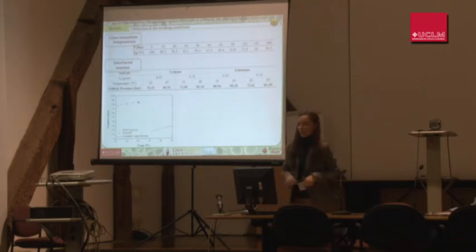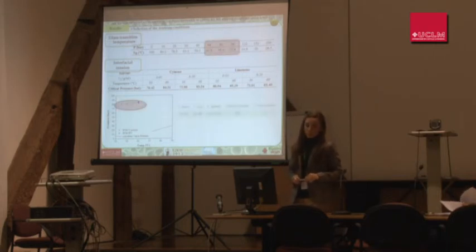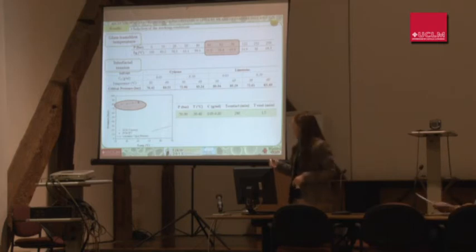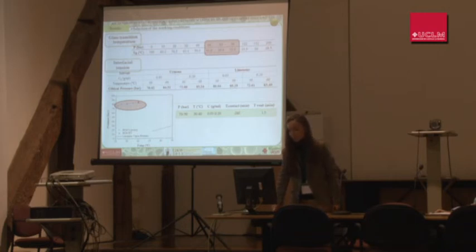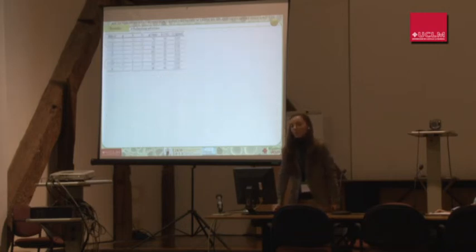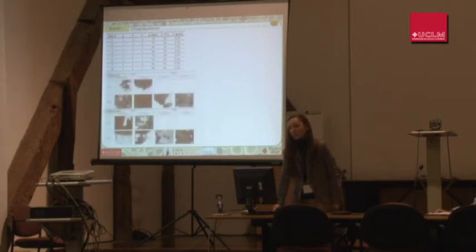So, as the foaming process should be carried out around the Tg zone and in a place where the interfacial tension should be the lowest, we decided to propose a design of experiment with these 3 variables, pressure, temperature, and concentration, at 2 different levels to study the influence on the microcellular foam structure. As we can observe, this is the design of experiment that we performed, and these are some of the most relevant microphotographs that we obtained.